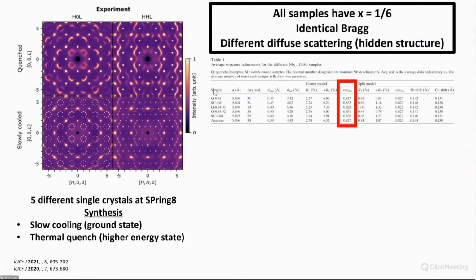But if you do the Bragg scattering, then it's interesting, because you get the exact same structure from these two crystals. All the samples we have done, the 5 samples, always have 1/6 vacancies. So the occupancy of niobium always comes out to 1/6. And the Bragg scattering and the refinement are basically identical. So if you were a structural chemist doing Bragg scattering, you'd say these crystals are identical. But clearly they are not, right? They have very, very different diffuse scattering.